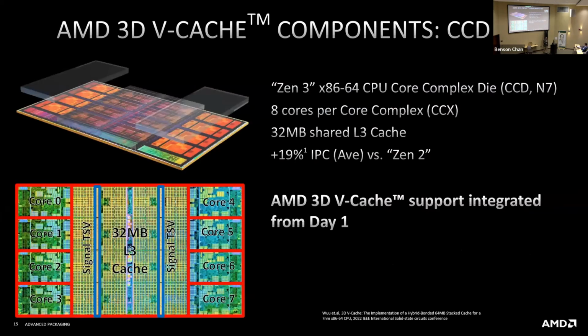The components of this particular architecture are the bottom die, which is the CCD. This is made of TSMC N7, where we have 8 cores in the die, which we're calling a CCX, a core complex, and it also has a 32 MB cache memory at the center, as you can see. This CCD connects to the L3 cache using the signal TSV arrays that you see in the center in the blue boxes.